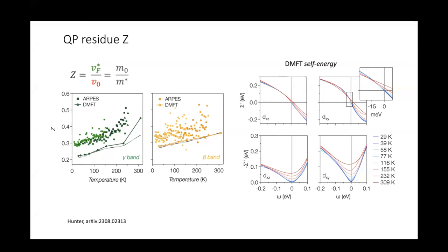Thanks. So I was just wondering if this gives any insight into why certain materials have resistivity saturation and certain materials don't. So is the suggestion that the non-saturation is because the quasi-particle weight is actually not disappearing, and when it saturates, it is? I think when it's saturated, it means that the mean free path remains quite large. So the mean free path remains large.